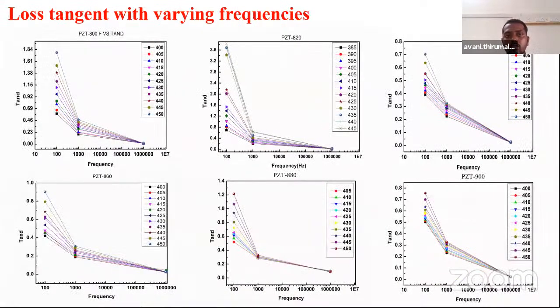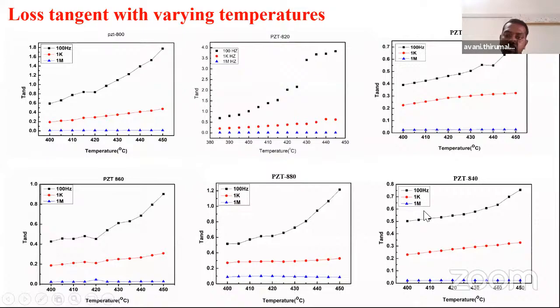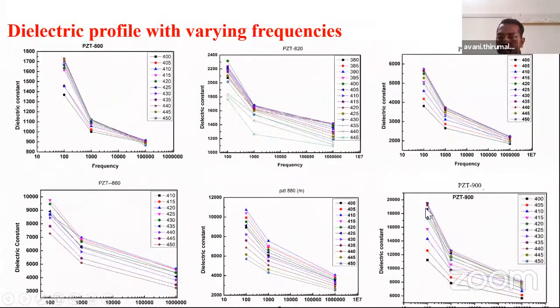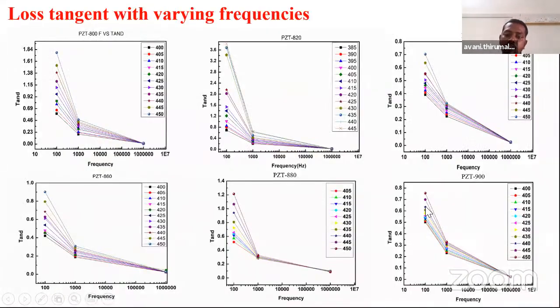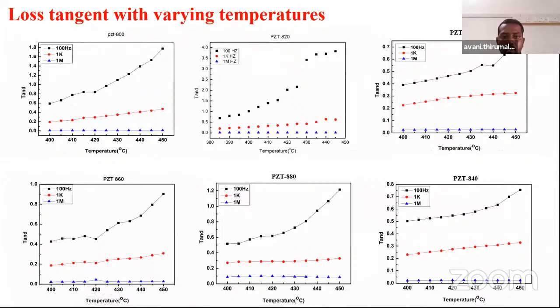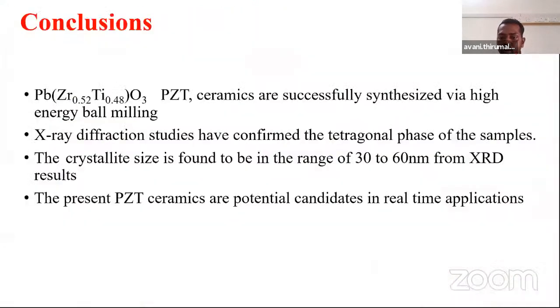These are the loss tangents with varying frequencies. Here, 400, 405, 410 are the temperature variations. If you go to the last figure, PZT 900, 430 is nearly the transition temperature. The losses are very, very low in that particular transition temperature region. This transition temperature plays the key role in ferroelectric materials. Not only ferroelectric materials, in every material the transition temperature is most important.